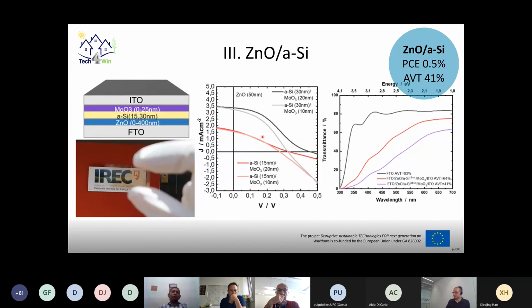Here you see this optimization in the middle. Zinc oxide, we already used the best one, which was around 50 nanometers. And then you see that JV characteristics are improving for the thicker amorphous silicon layer, as you might imagine. So the 30 nanometer, we're getting better current and a bit better VOC as well. And also for the moly oxide, it seems the thicker moly oxide is giving the best results for the moment. What do we have? We quite easily in the first run, we got to a 0.5% efficiency with an AVT of 41% in the case of the 30 nanometer of amorphous silicon.